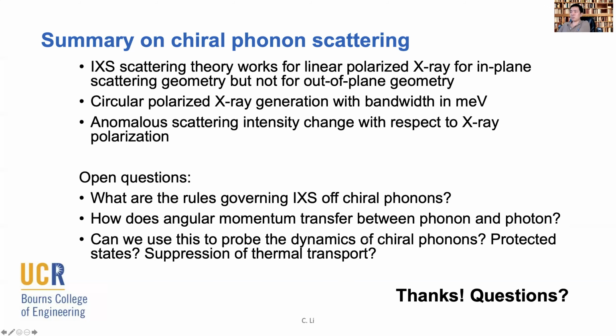And the last is a more derived problem, more on the material side. Assume that we are able to probe the chirality of the phonons, what can we do with this? Is there a way we can use this to control phonon-phonon interactions? For example, is there a way we can create a protected phonon state by working with their chirality? Maybe we can use this to suppress or enhance certain phonon-phonon interactions, which can have implications either for thermal transport or for other things like even spin-phonon interactions. Because spin does carry angular momentum, and the magnon does carry angular momentum. That might also be relevant in terms of the interactions.